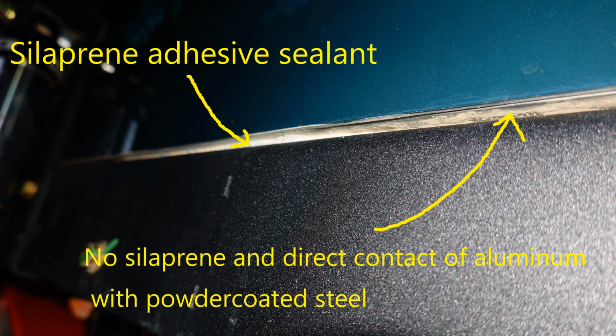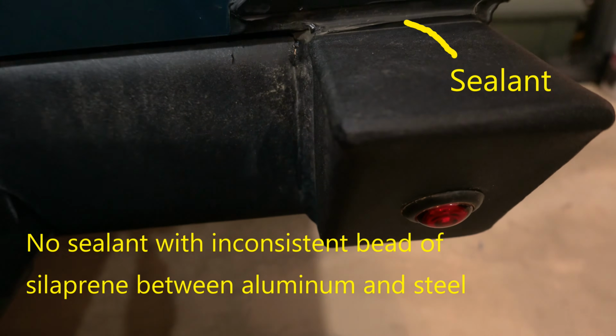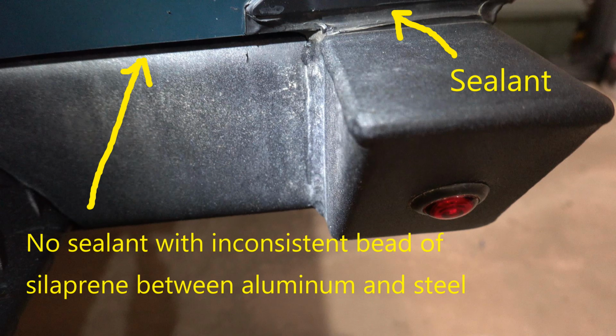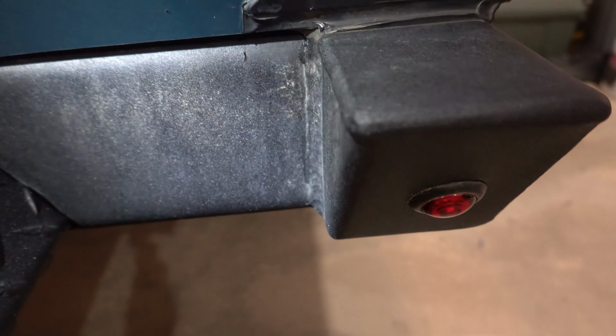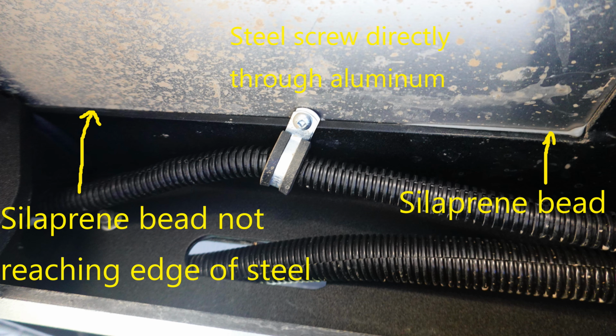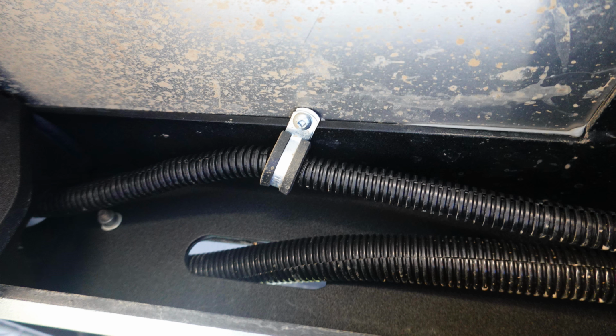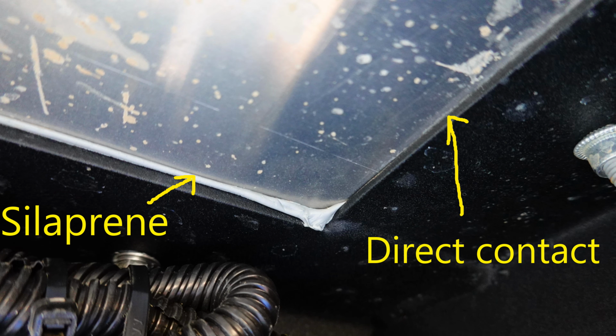Here there is some Silaprene visible between the walls and the chassis, but clearly there are areas where there is close contact or direct contact without isolation. It looks like a bead of Silaprene was put on the chassis, and when the structure gets compressed down, there's varying degree of spread, and it doesn't cause consistent isolation between the two. On the underside, the steel crossbeams do not consistently have Silaprene isolating the steel from the aluminum bottom plate, and stones will get in and abrade away the powder coat on the steel chassis, and water will get in